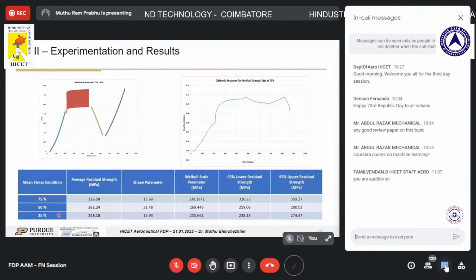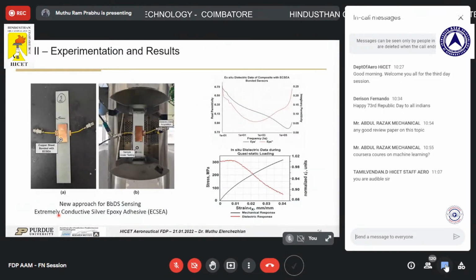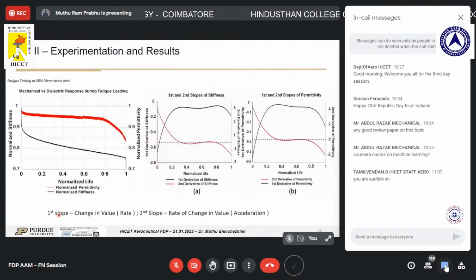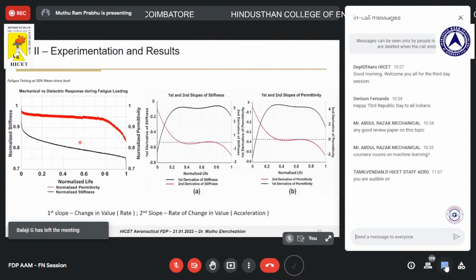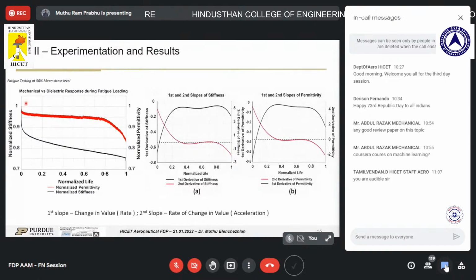So how I actually use this data is that we first obtain the first slope and second slope values. We have the stiffness curve over here, which is normalized, which is the black curve. And we also have the dielectric property curve, which is the permittivity curve, shown in red. Once you can see, at almost 80% of life, or after 75% of life, the permittivity curve shows a reduced behavior over here. But the stiffness curve is still straight, as you can observe directly.